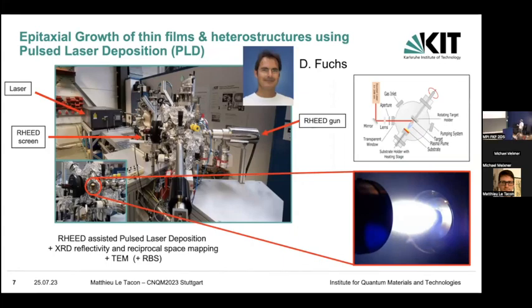He's doing this with pulsed laser deposition. So you basically have a target in a vacuum chamber in which you control the oxygen atmosphere. You sublimate your target and you deposit it at high temperature on the substrate. You do this with electron diffraction to monitor the layer by layer growth. And we have everything set up to look at the reflectivity of X-rays and make reciprocal space maps to actually structurally characterize those films.